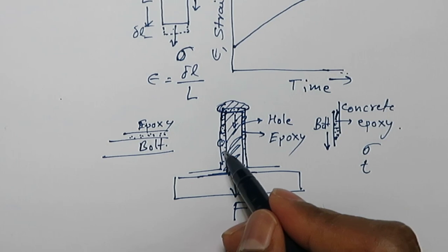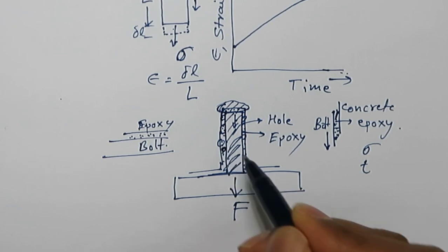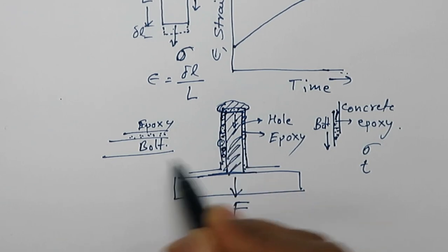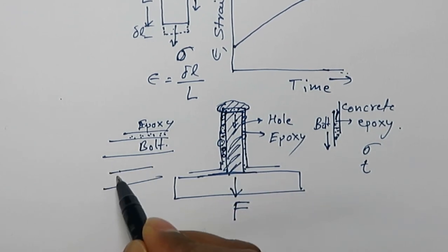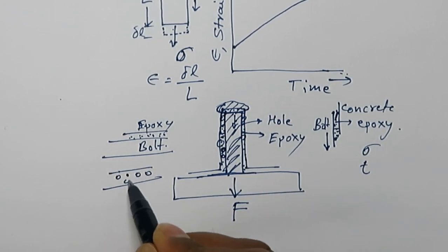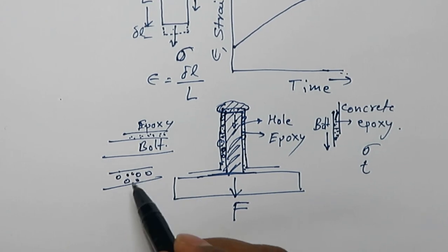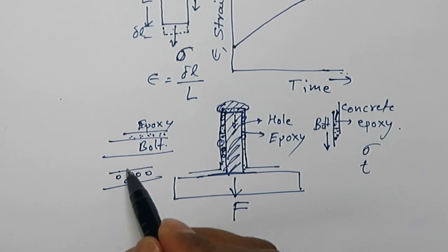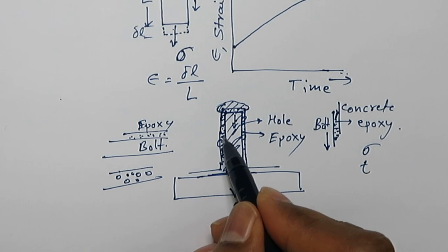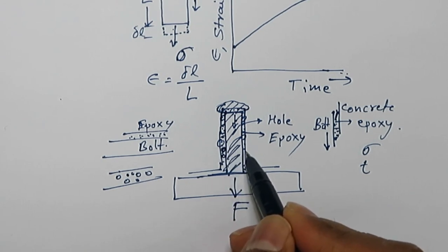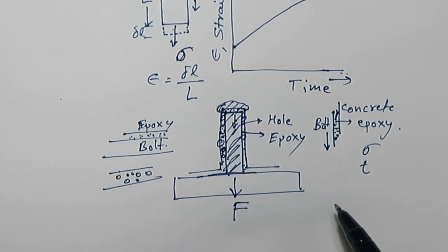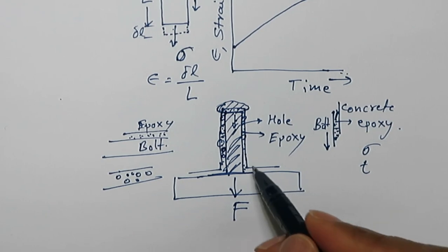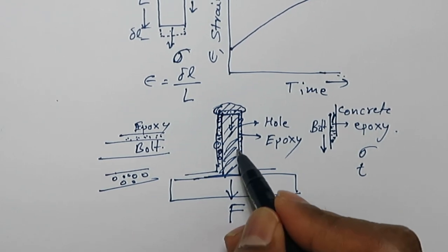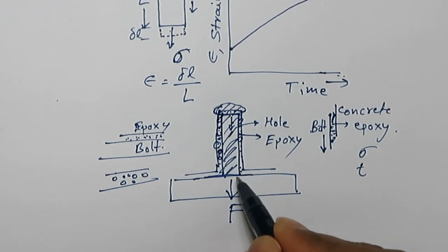Also, it was found that there were a lot of voids inside. So when epoxy has voids, basically the strength of epoxy is reduced. So because of the voids, the strength was also reduced. So there were several problems in this case, and that led to pulling of the bolt out of this hole.